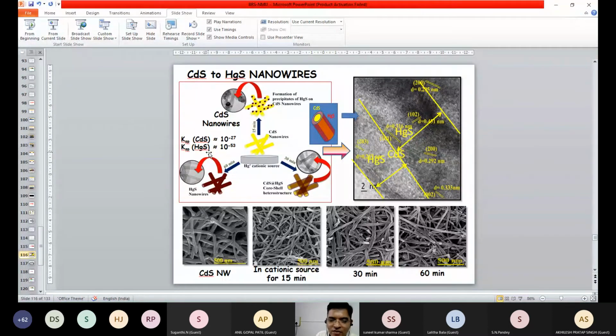Then whatever CdS is formed, we dipped inside the mercury solution. Mercury sulfide has a solubility product of 10 to the minus 53, and CdS has 10 to the minus 27. So some cations of the cadmium sulfide, that is Cd, get replaced by Hg. Interesting, right? Some cadmium ions get replaced by Hg ions. So here you can see that inside it is CdS, and the outer part, which is in contact with the Hg solution, has Cd replaced by Hg.